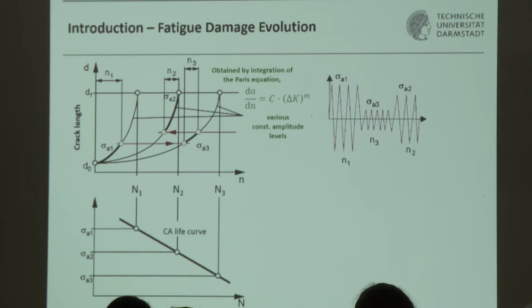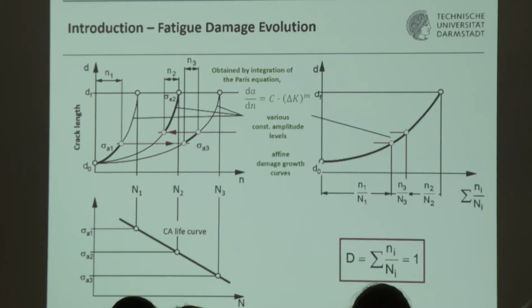So, however, this is not the real end of the story, because you can replot these graphs from fracture mechanics in a normalized way, take each of these crack growth lines and divide the life axis here by its end value. And if you do so, fracture mechanics tells us that you end up with only one line. And if you have this situation, we call that affine damage growth curves. And in this situation, we can repeat our experiment.